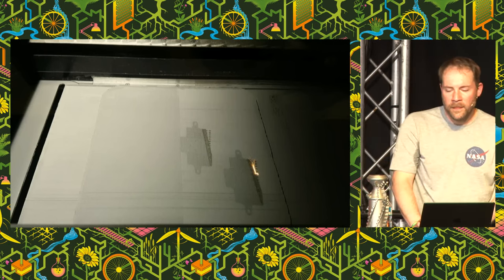And this is where 3D printing comes into play. So the kind of 3D printing we're using is obviously metal 3D printing, and it's specifically a technique called powder bed fusion. And the way that works is that you lay down a layer of powdered material, powdered metal, the particular alloy you want to make the thing out of. It's typically maybe particles of 30 to 60 microns thick, which is sort of talcum powder consistency. You lay a layer of it down, and then using lasers, much like a normal plastic 3D printer, you run a contour pass around the edge and then hatch with a laser a fill pass in order to melt the powder together. And then an arm comes over the top and lays another layer of powder down.